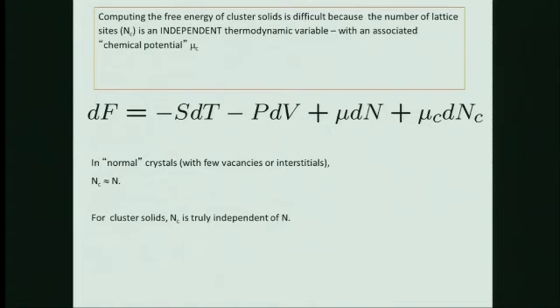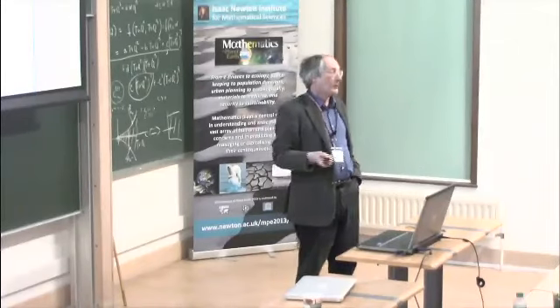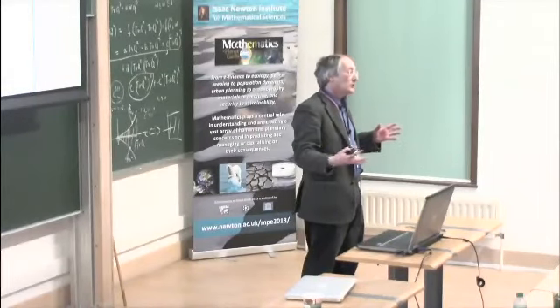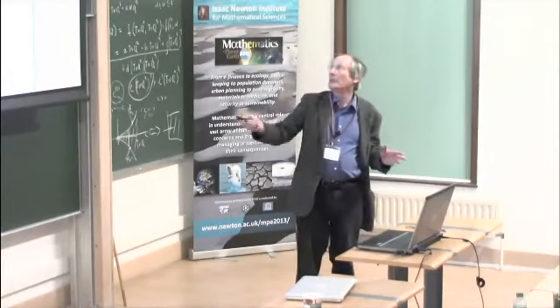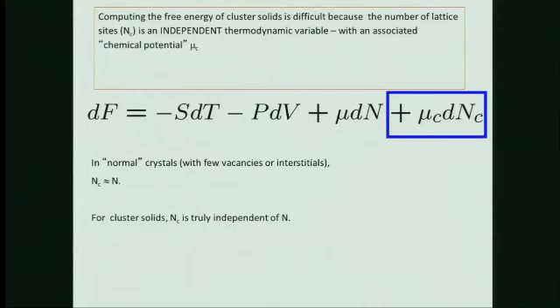But here you can't do that, because if you look at the variation of the free energy, you can vary it by changing the temperature, the volume, the number of particles, but actually also by varying the number of lattices. Now you have to be very careful with this, because this term is a bit special. In the end it will go away, and the reason why it will go away is that the crystal, of course, searches that number of lattices that minimizes the free energy, and therefore the coefficient is always 0.